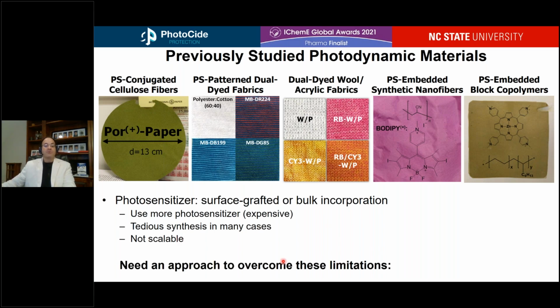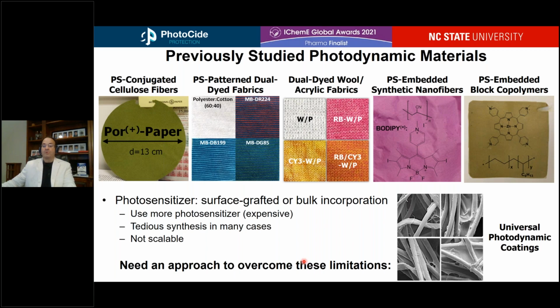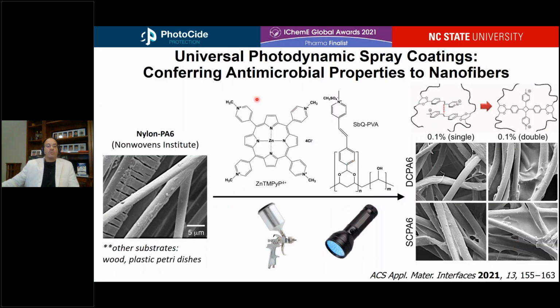So we need an approach to overcome these limitations, and the approach that we have adopted is the use of universal photodynamic coatings. And so to introduce the coatings themselves, we can take a common photosensitizer commercially available and mix it into a bicomponent formulation with a photocross-linkable polymer, this polyvinyl alcohol polymer, SBQ-PVA, in the presence of a UV cure, creates this cross-linked web that you can see here on these SEM images on the right-hand side.